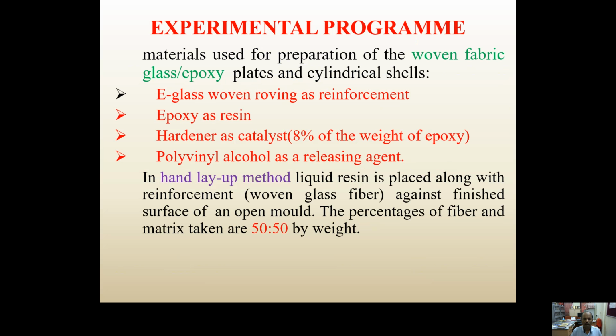Coming to the experimental program, the materials used are woven fabric glass epoxy: E-glass woven roving as reinforcement, epoxy as resin, hardener as catalyst, 8% of the weight of the epoxy, and polyvinyl alcohol as the releasing agent. The fabrication has been done with the hand layup method. Liquid resin is placed along with reinforcement, the woven glass fiber, against the finished surface of an open mold. The percentage of fiber and matrix taken are 50:50 by weight.